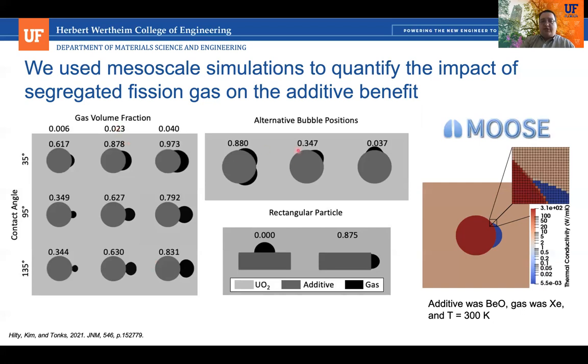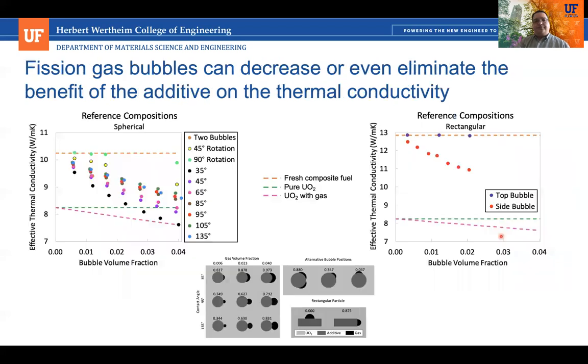And we also looked at different positions. In these cases, the bubble is in the direction of heat transport, which is to the right. But then we looked at having bubbles on the top and bubbles on the bottom and maybe multiple bubbles. And we also looked at rectangular particles instead of spherical particles. And so we represented them, and we used MOOSE to calculate their effective thermal conductivity, where we assigned different thermal conductivity to the additive, the UO2, and to the gas.